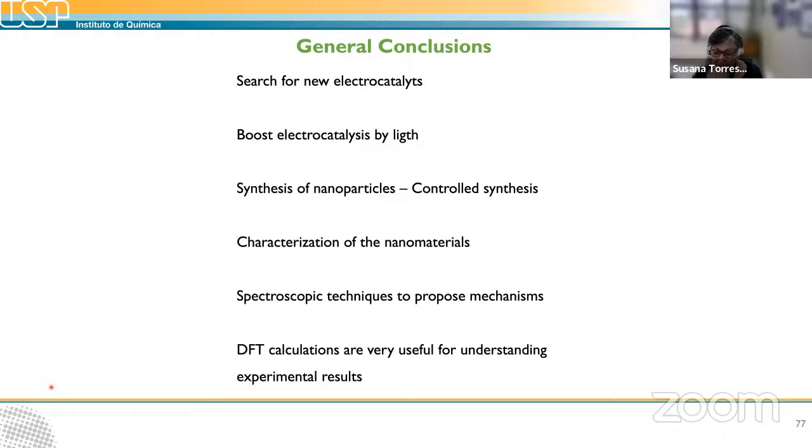Yes, okay, you can also measure, for example, in the case of batteries, normally they measure by physical methods, for example by BET. It is very normal. But when you have to determine the electrochemical area, there are different methods that we have no time here to discuss. It can be by copper UPD, if you have gold, for example, or by voltammetry, where you have a region with no Faradaic current. It depends on the material.